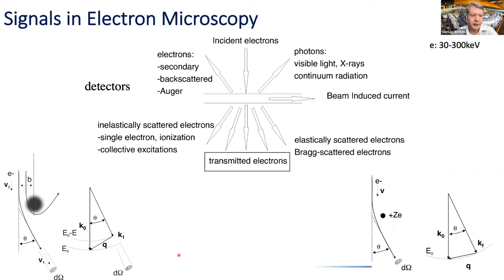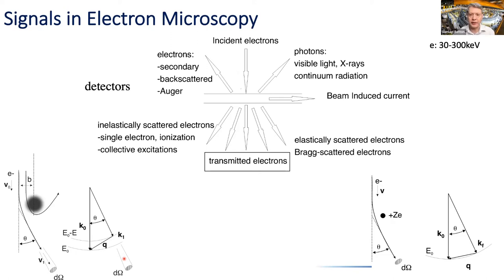With a spectrometer, we can measure the energy that inelastically scattered electrons have lost when passing through the sample. The difference between elastic and inelastic scattering, besides the energy loss, is the momentum transfer. We have an incident wave vector and a final wave vector, with a scattering vector defining the process. An aperture collects the transmitted electrons — it can be large or placed off the transmitted direction. This differs from X-ray absorption where there is no momentum transfer.